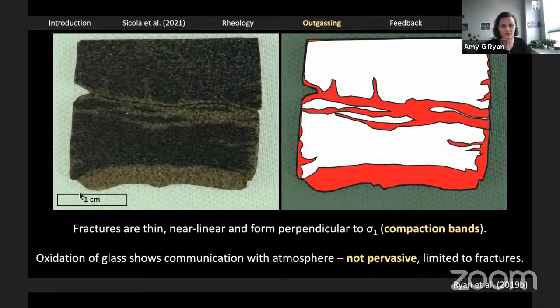A bunch of fractures have formed down here, giving this region of green. But I want you to mostly focus on the 1 or 2 fractures that formed up here in the center of the sample that illustrate a little bit better their geometry and their thickness. What you can see from these green traces is that fractures that form, these outgassing pathways that formed during my experiments, are thin and near linear, and they form perpendicular to the compaction direction. This makes them compaction bands.